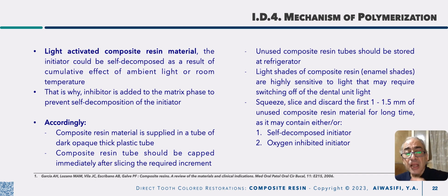When you have an unused composite resin tube that has not been used for a long time, you should squeeze a slice of 1 to 1.5 millimeter thick of this composite and discard this slice, because it may have self-decomposed, or it may contain an oxygen inhibited layer.